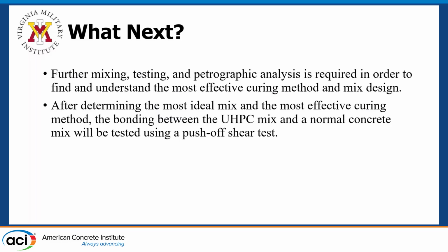After determining the most ideal mix and the most effective curing method, bonding between the UHPC mix and our normal concrete mix will be tested using a push-off shear test. We currently have at VMI 8 beam forms to go back and recreate based off Mr. Butler's research from last year. We're going to be making those with normal concrete, purposely breaking portions of them and then adding our best mix onto that, and then seeing based on a push-off test how well that bonds.